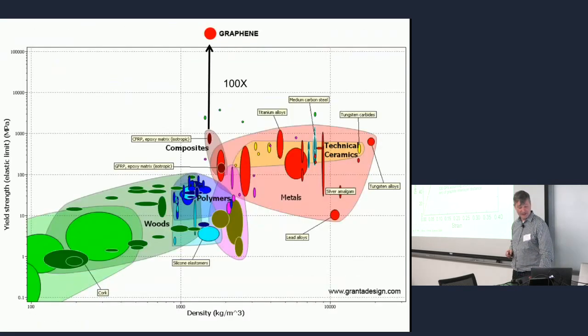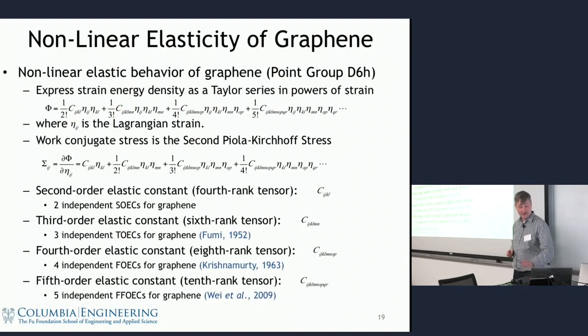And this was the kind of endeavor undertaken by a student in Jeff Kaiser's group with Chris Marianetti, a theorist as well. What they did was really go back to the drawing board and think about how you look at the stress strain behavior of this 2D material under very, very large strain. First you realize that this material isn't necessarily isotropic, and so all of these elastic constants are not scalars, but tensors. Now you do this beautiful tensor expansion. So there's your strain, and this is your stress. This is all your strain terms here. Your strain is now this eta, so all these indices are either x and y, 1 or 2.